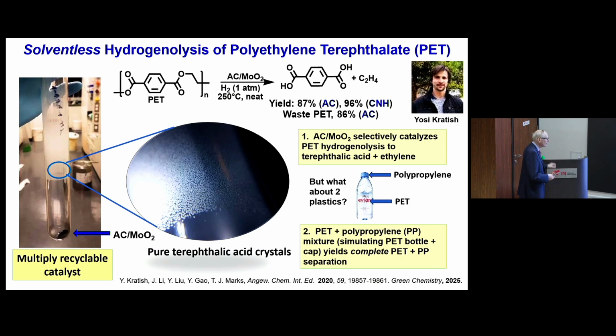So this is PET. Now at the beginning, how do you grind up the PET? We used a cheese grater that you use for cheese. Now we have something much more sophisticated. And what happens is you reach the point where the PET melts, and this is the reaction here. So PET goes to terephthalic acid and ethylene, in very high yields. And the PTA is very, very pure, so no solvent.